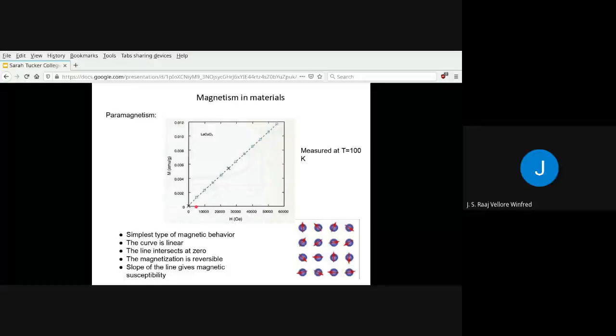The behavior is linear. On the x-axis, you see the applied magnetic field, and on the y-axis is the magnetization of the sample. As you can see, as you increase the applied magnetic field, the magnetization also increases. Which means that initially, at zero external magnetic field, the atoms are randomly aligned. But as you apply an external magnetic field, the magnetization goes up. And this magnetization is reversible, which means that if you remove your applied field, then the atoms' moments once again align randomly. And the slope of this line gives the magnetic susceptibility.